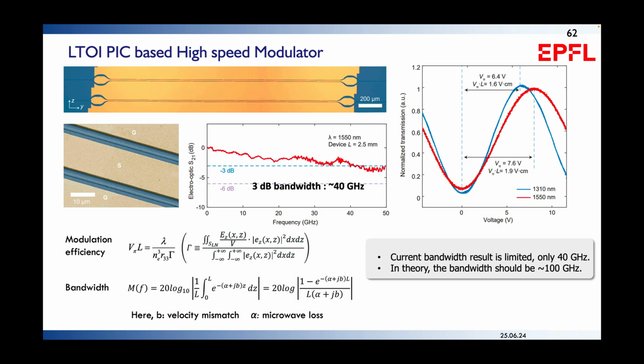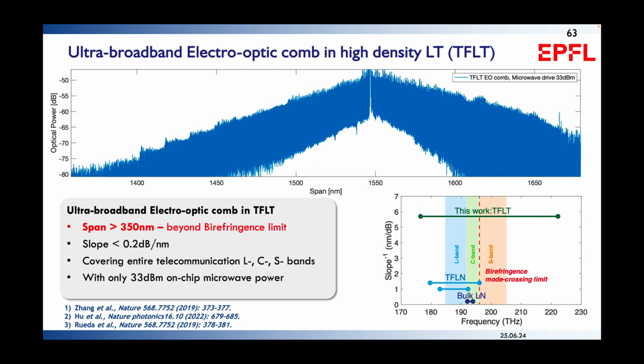Now, another device you can make are electro-optic combs. Instead of using a Kerr comb generation mechanism, you can make an electro-optic comb by just driving a modulator very hard or resonantly enhancing it. Here is an example of a lithium tantalate EO comb that comprises more than 1,000 comb lines, driven with 7 watts of RF power. The span here is significantly enhanced compared to lithium niobate because you have lower birefringence.